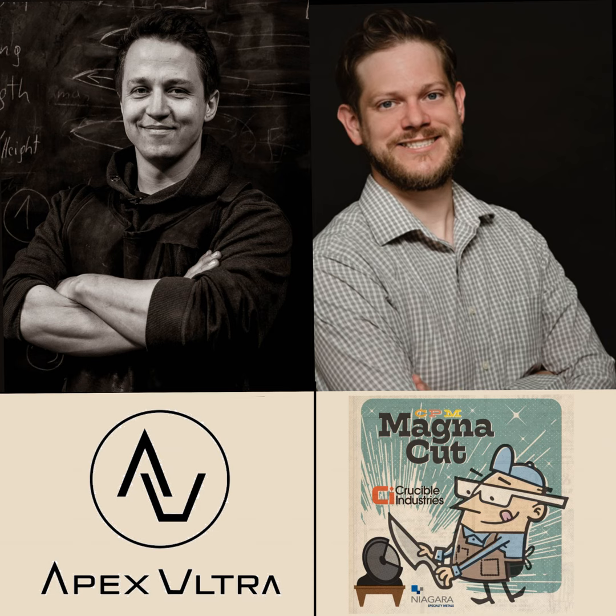Yeah, and these aren't just nerdy things interesting to metallurgists. When you measure the toughness, like impact toughness, you break something. If it's made with powder metallurgy, it is more difficult to break. It takes more energy to break. And so, having a homogeneous, fine microstructure leads to better properties. And in the case of MagnaCut, the steel probably would not be possible to produce using conventional methods. You would forge it and it would just break apart.